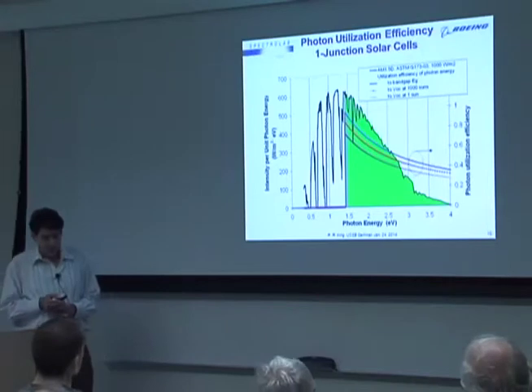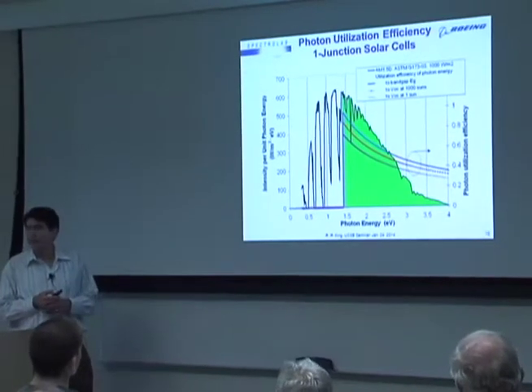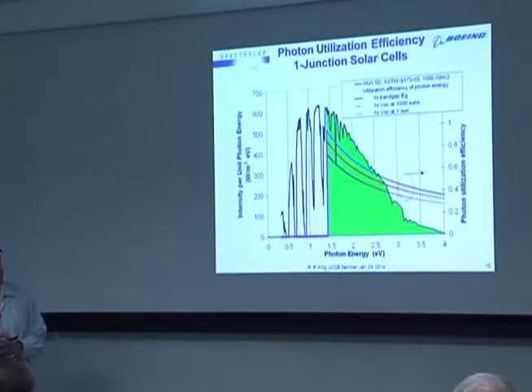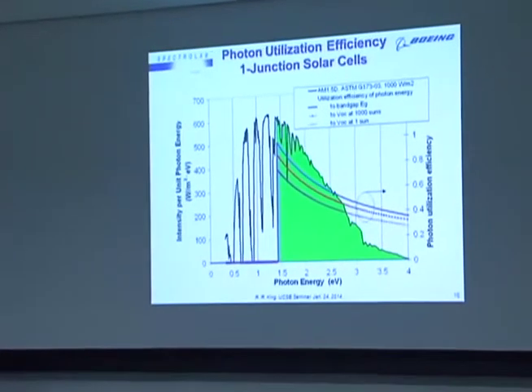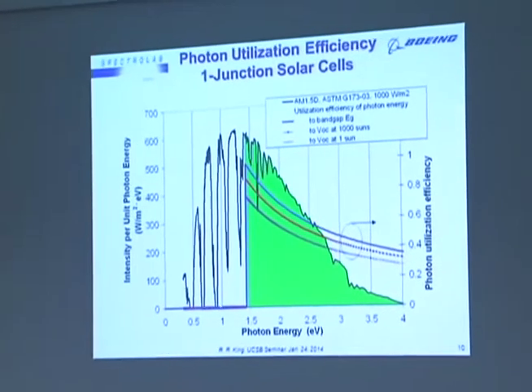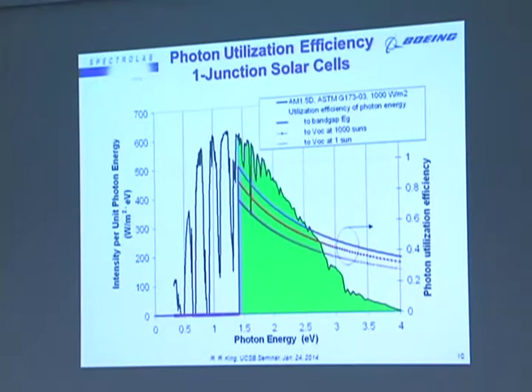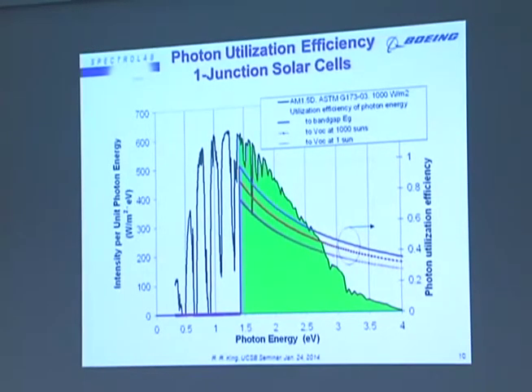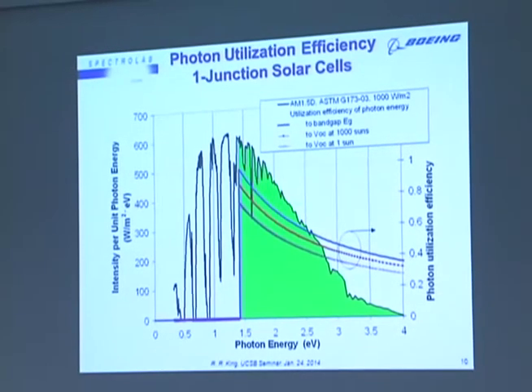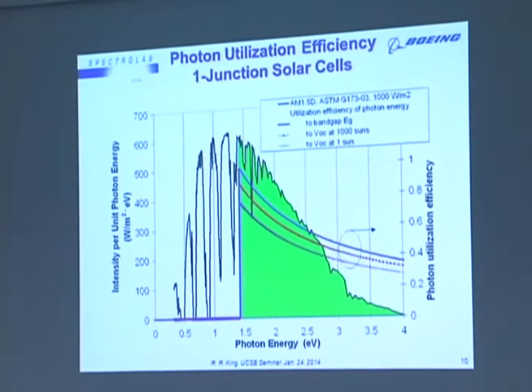And that's due to the phenomena that I'm sure you're familiar with. Photons with energy below the band gap can't contribute to photogeneration. They can't contribute to the current of the solar cell. And for photon energies above the band gap, you have a photon utilization efficiency that drops off because these higher energies are not able to be fully utilized by a material with a single band gap.